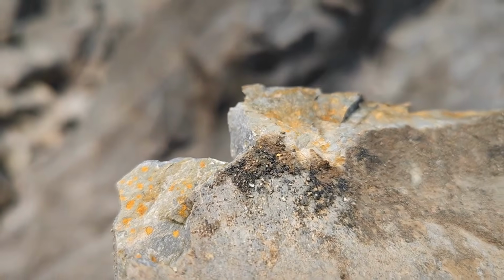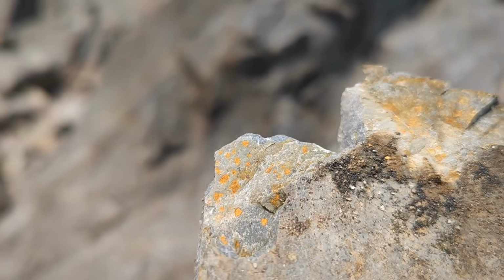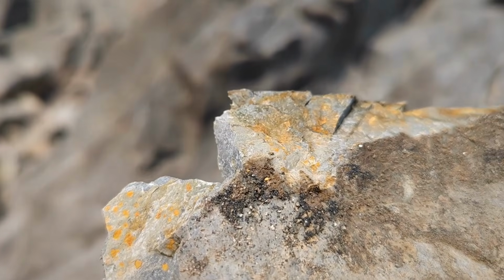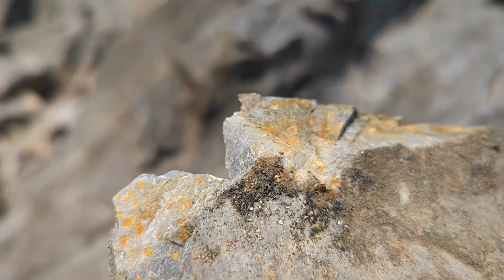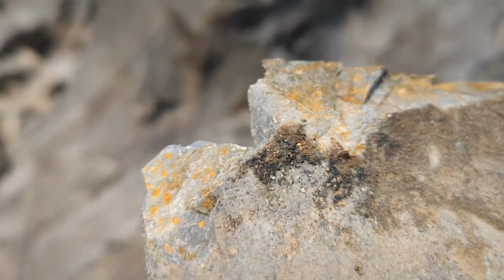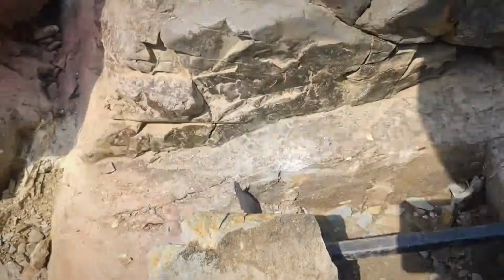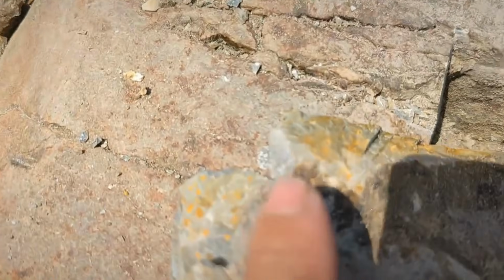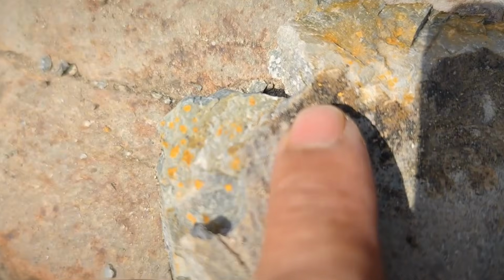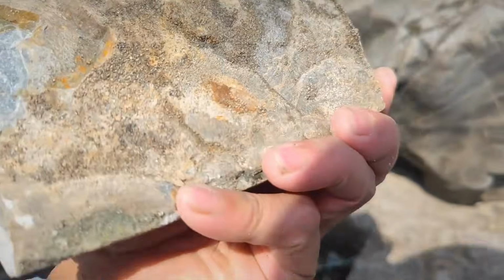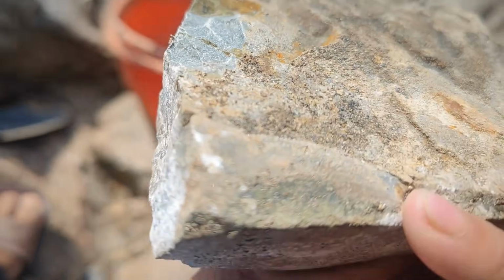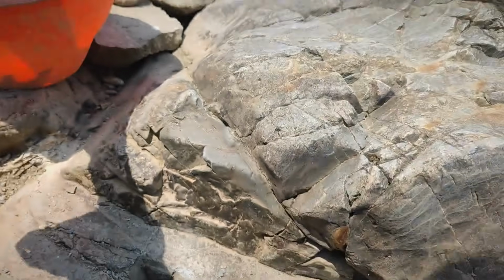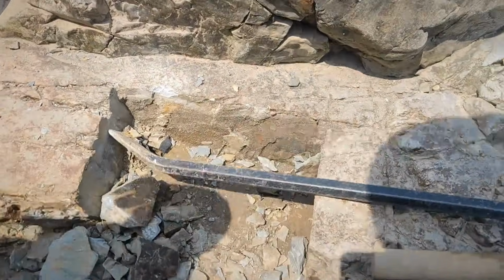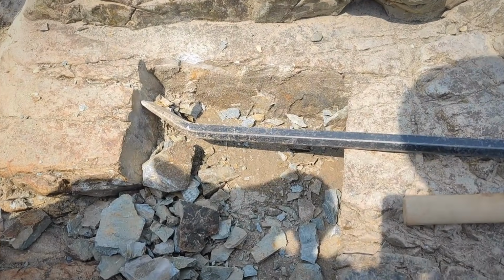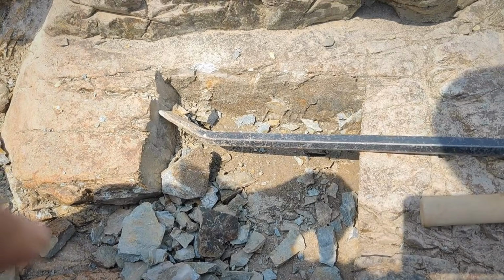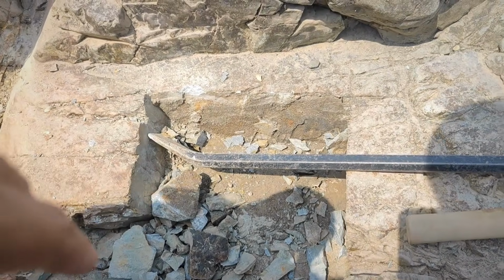Textural combinations are even more telling. A piece showing sugary texture near the surface, vuggy pockets deeper in, and banding across a fracture line reflects complex, long-term hydrothermal flow, exactly the scenario in which gold is most likely to have precipitated. These textures also dictate how gold can be recovered. Vugs may hold visible gold. Sugary quartz may require fine crushing. Banded samples may show gold bound in sulfide-rich bands.